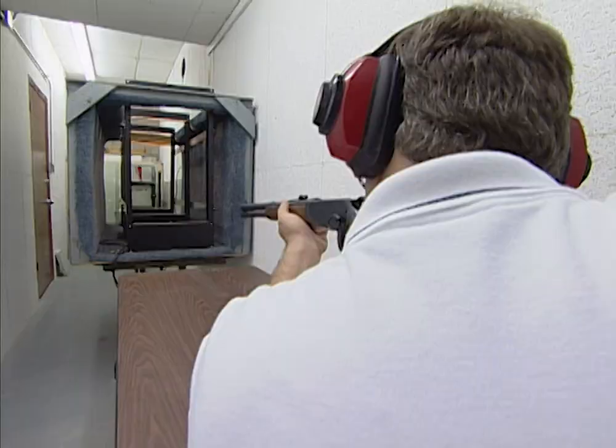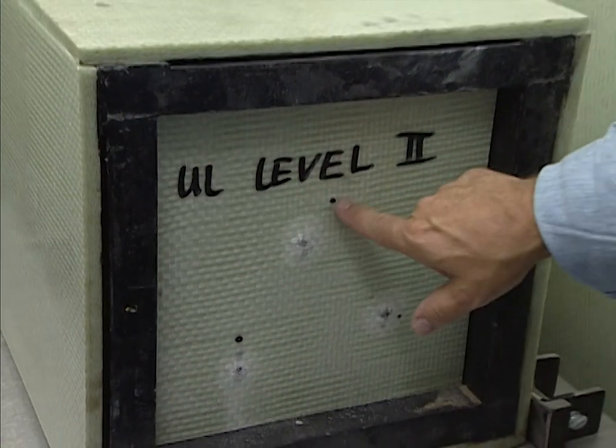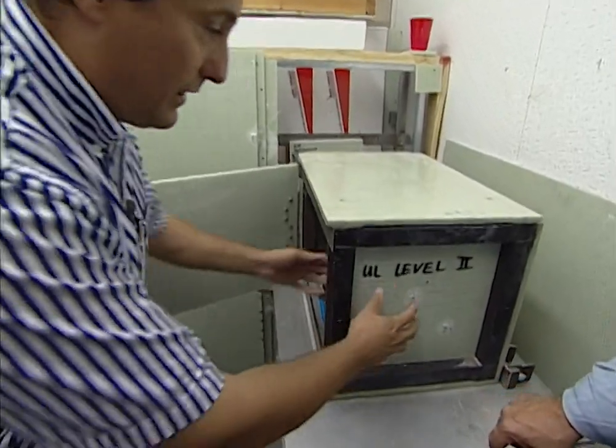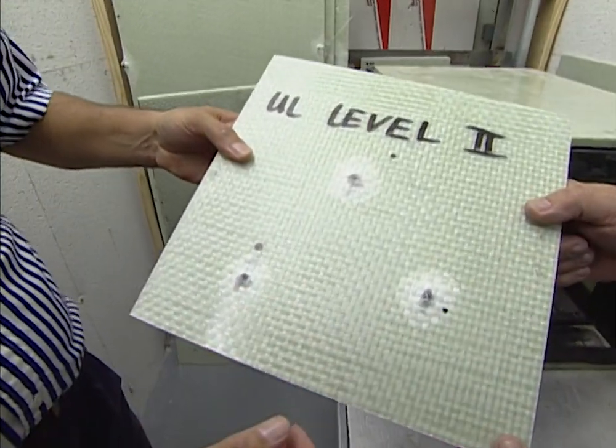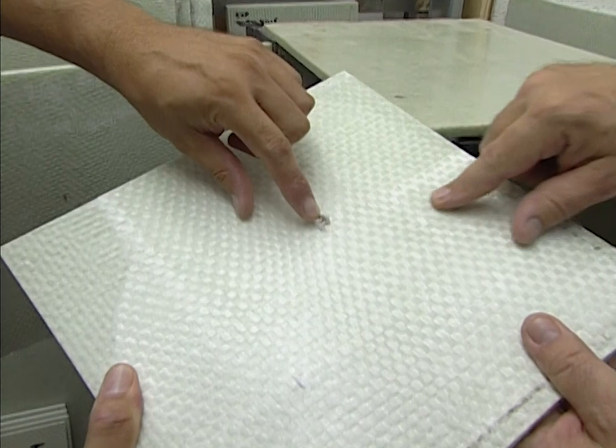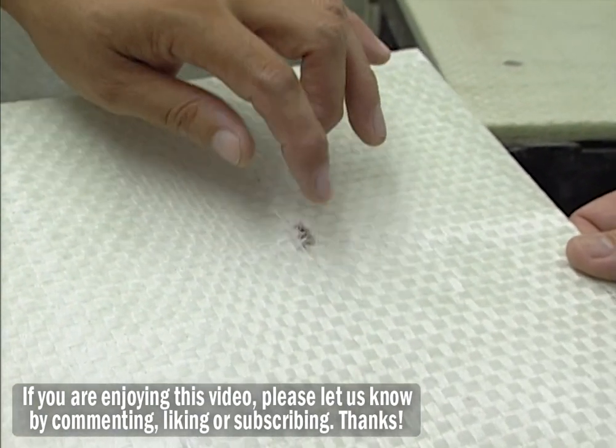The company has its own indoor gun range to ensure that the panels are not only bullet resistant but ricochet resistant as well. Wayne shot this target three times with a .357 Magnum. Let's go ahead and open this and get the panel out and see what we got. As you can see, three rounds of .357 Magnum. Looking at the backside, you have a perfect example of how the bullet has been defeated and contained within the fibers of the panel. It passed the test — no penetration. It's locked within the fibers.